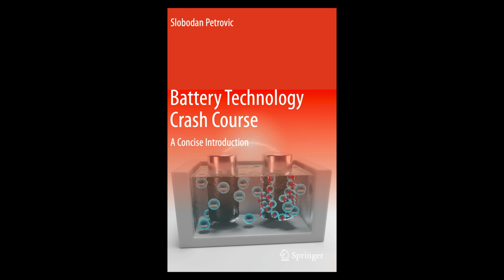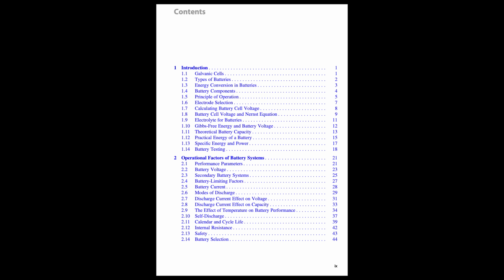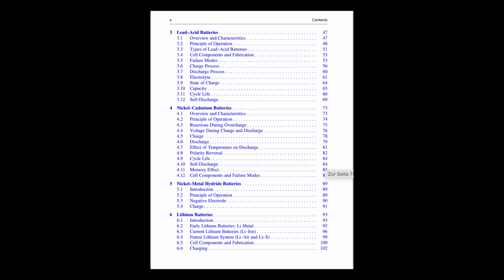Petrovic also mentions additives, like calcium versus antimony. Yes. These are added to the lead grids that hold the active material. Adding calcium helps reduce water loss, gassing, self-discharge, and corrosion. Good for maintenance-free SLI batteries. Okay. Antimony makes the grids stronger, more resistant to the stresses of deep discharge cycles. So it's often used in deep cycle batteries for things like golf carts or solar storage. But antimony can increase water consumption and self-discharge compared to calcium.